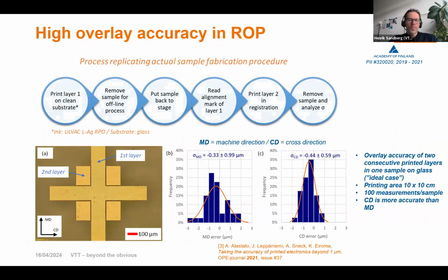I mentioned the overlay accuracy or the registration accuracy in this device. This has been optimized in several projects as well to reach as high as possible, so that it's actually on the same level as the printing resolution. Otherwise, it doesn't make much sense. But as you can see from the results, it's on a high level, and we see an error in the micrometer range maximum for a large number of samples over the full printing area. It's 10 by 10 centimeters in this case. Our machine can handle up to, I think, a little bit more than 200 times 200 millimeters. But the quality, due to the process design, is very uniform over the whole area.